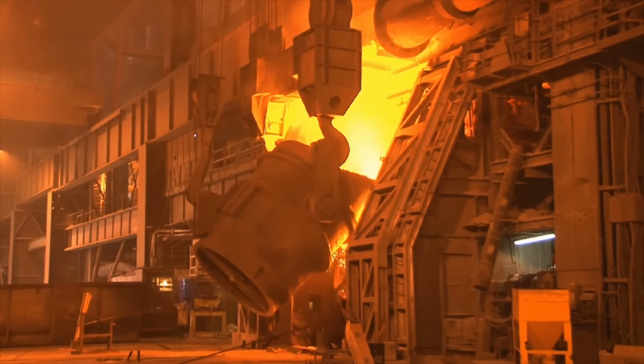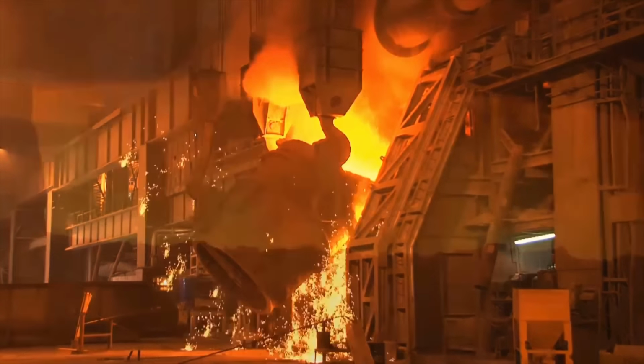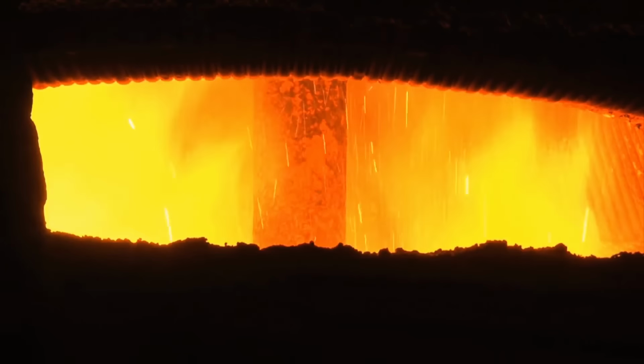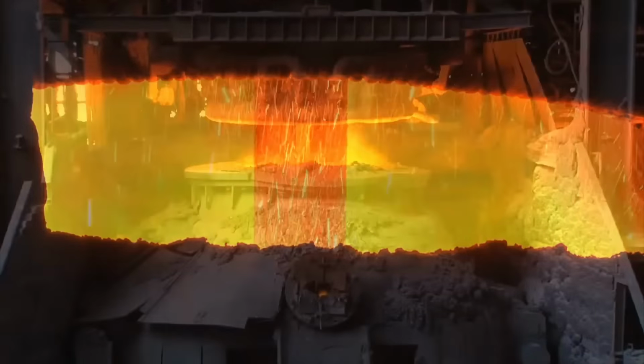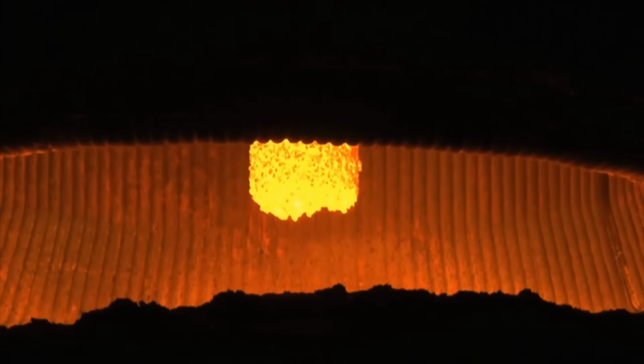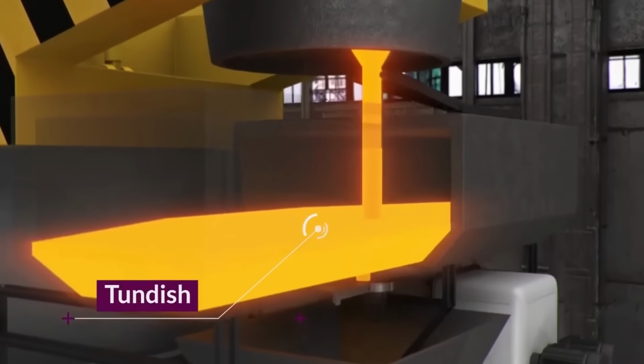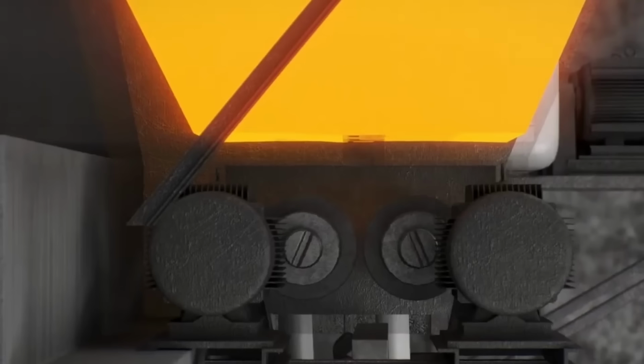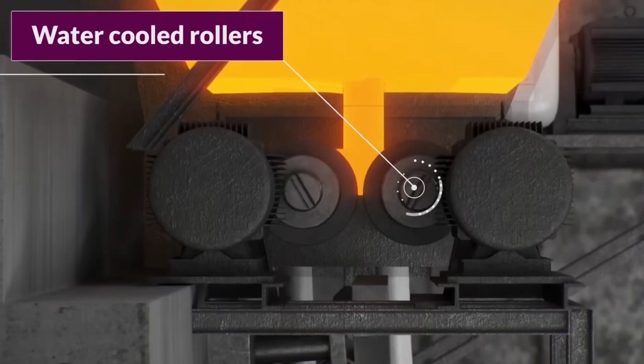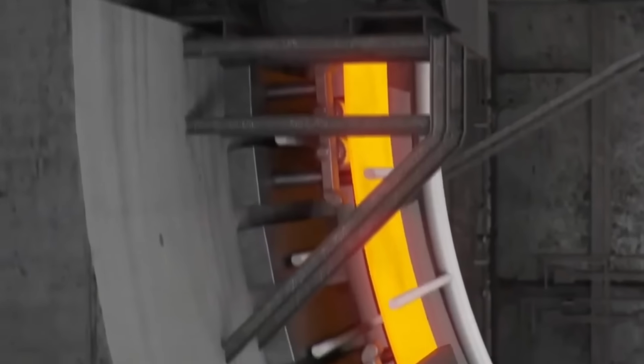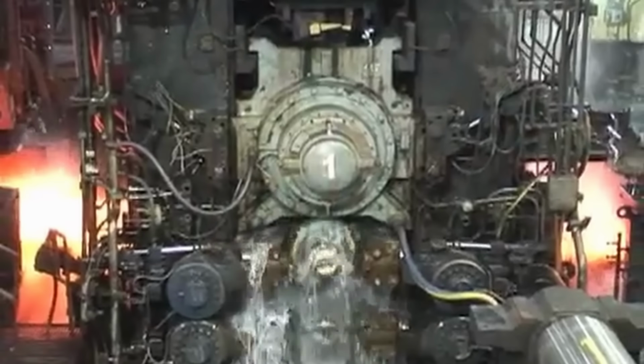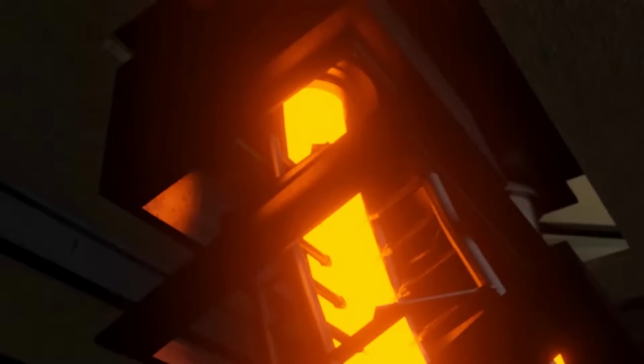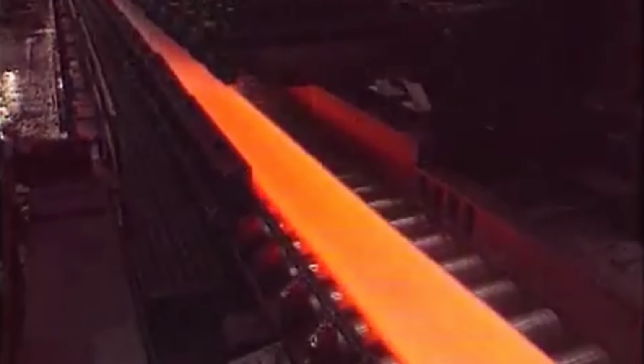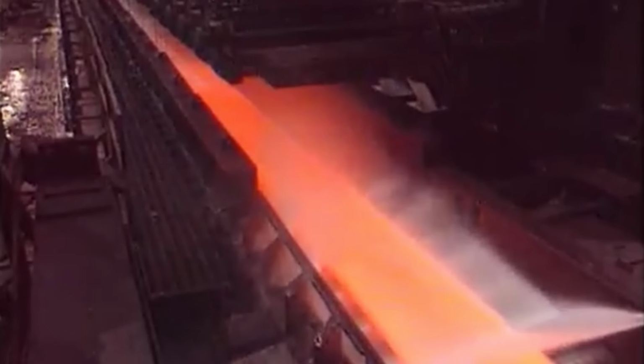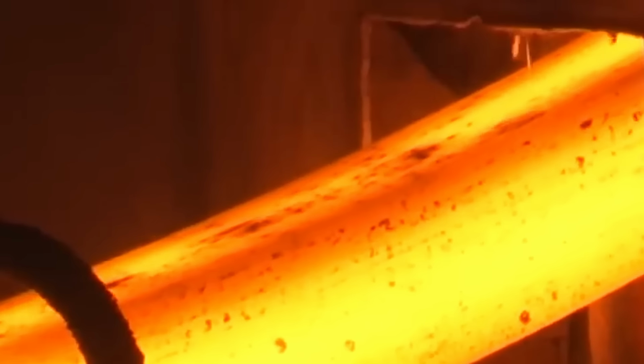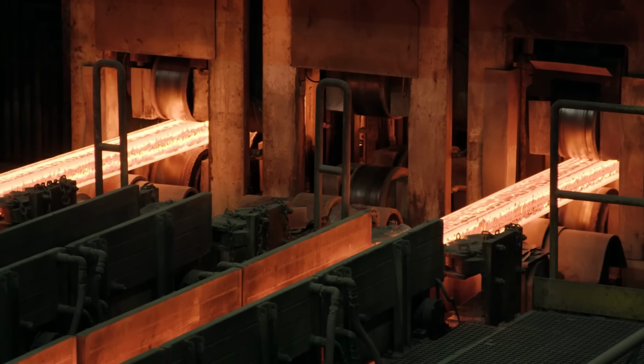This is where modern steelmaking shows its efficiency. Continuous casting replaced the old ingot method, where steel was poured into individual molds and allowed to cool completely. Instead, molten steel flows continuously into a water-cooled copper mold. The copper conducts heat rapidly, so the outer shell of steel solidifies almost instantly upon contact. As the solidified shell moves downward, the liquid core slowly freezes from the outside in. The casting machine carefully controls this cooling rate because it affects the internal structure of the steel.